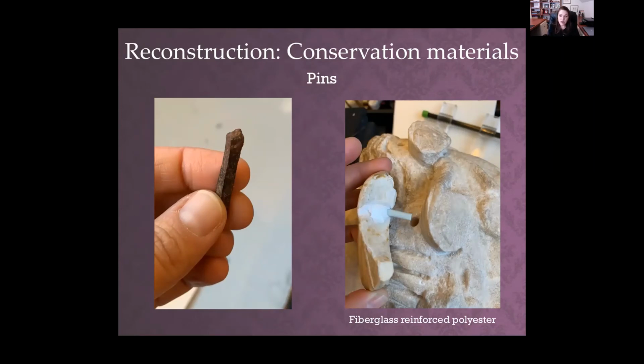Pins have been used extensively in restorations for hundreds of years. And the history of pins is actually really fascinating because in Florentine tradition, they would use a copper alloy pin, where just down south of there in Rome in the 17th century, they often used iron pins. So it was very regional. The pin you see on the left is a square profiled iron pin that was removed during treatment. It was in the leaf that you see on the right. But because iron, if it is exposed to moisture or high humidity, will expand and the corrosion product becomes larger than the iron itself, thereby causing stress and strain on the marble and possible cracking. We would never use iron today.